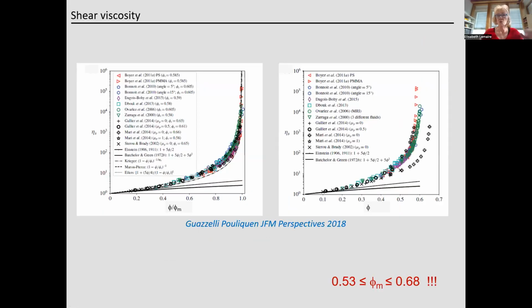Okay, so if you look at all the numerical and experimental results in the literature, all these results have been collected by Elisabeth Guazzelli and Olivier Pouliquen. And here you can see that it's right, the relative viscosity is a function of phi over phi m. But if you look in more detail, you can observe that the value of the jamming fraction, phi m, varies in a wide interval. And the reason for this variation of phi m is not completely clear.